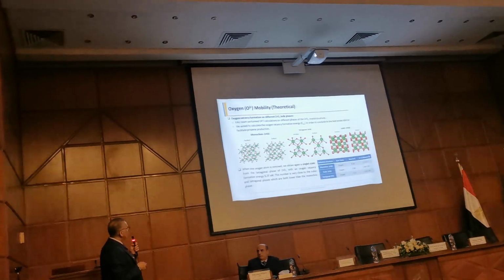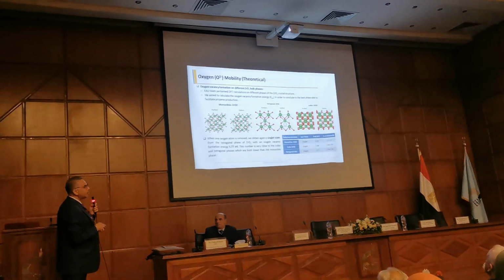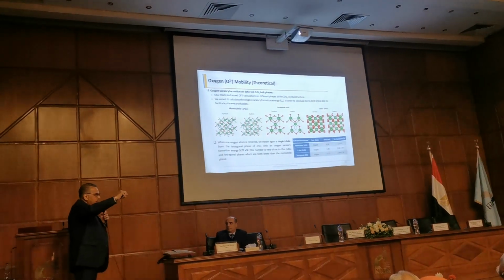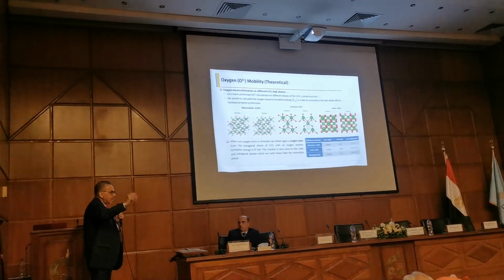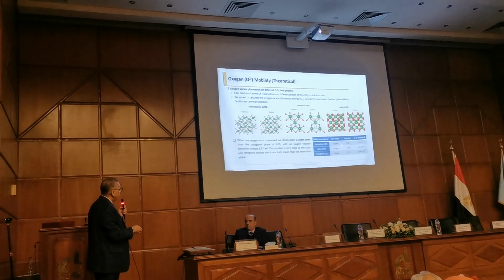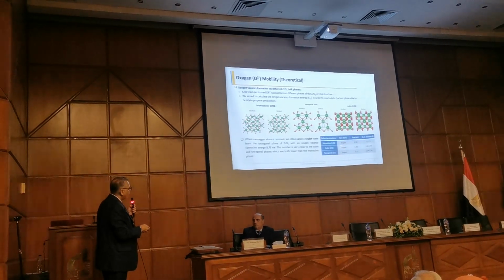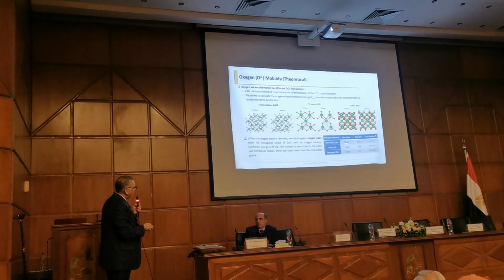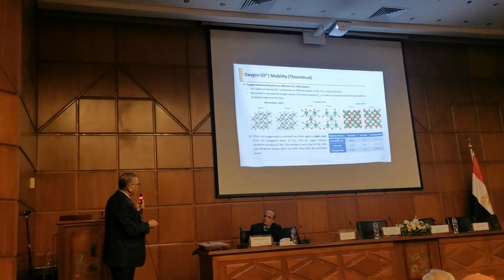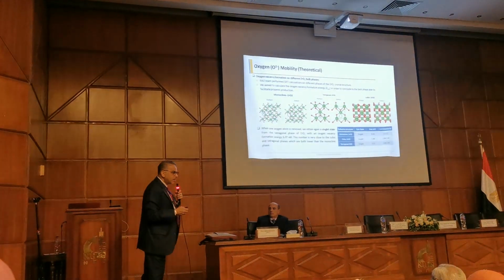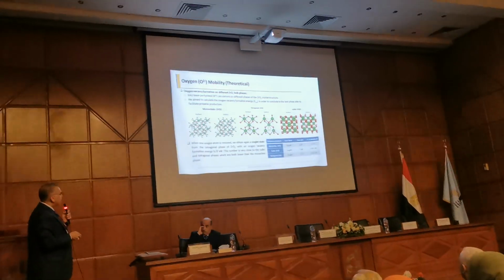According to the calculations, we removed 1 oxygen from the surface, just the top surface, not the bulk of the zirconia, taking 1 oxygen atom and seeing how much energy is required. So we find that the tetragonal and the cubic phases are the better phases for the zirconia instead of using the monoclinic. So we don't need to synthesize monoclinic, it's better to obtain the cubic zirconia or tetragonal zirconia in order to have a good support.